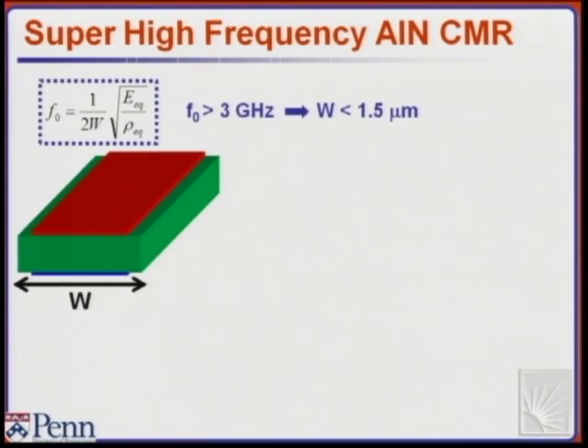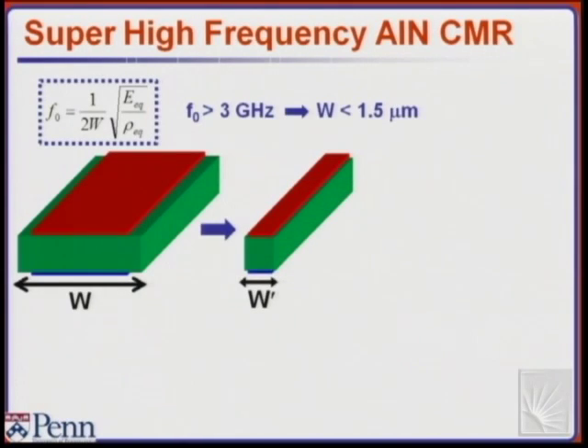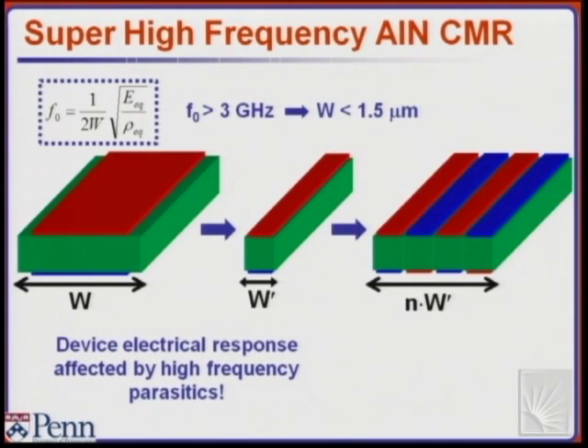Anyway, but we're interested in scaling, right? So we want to go smaller and we want to make the device smaller, especially we want to go above 3 gigahertz. So how do you scale? Well, the frequency equation is relatively straightforward. It is 1 over 2W times the square root of the Young's modulus divided by the density, which is actually the acoustic velocity of the material. That's constant, so you just have to scale W, right? Make W smaller, smaller than 1.5 micron, and you're going to get to 3 gigahertz. But that's a problem. We've already seen that for making devices above 800 megahertz and so forth, you really need to make that array, right?